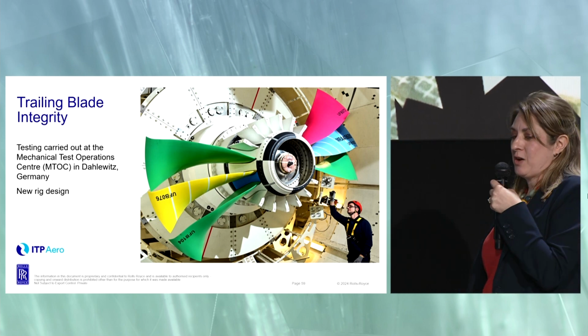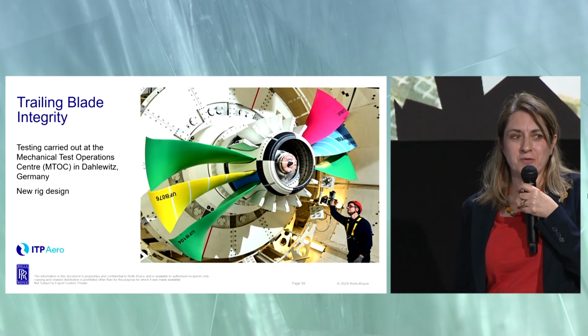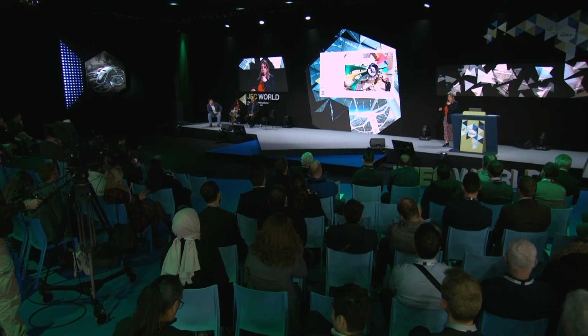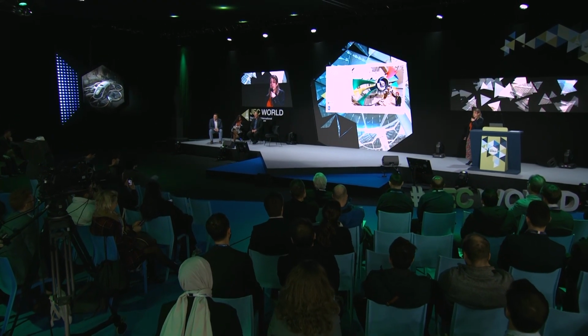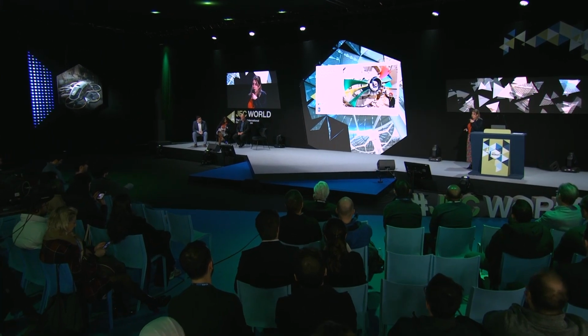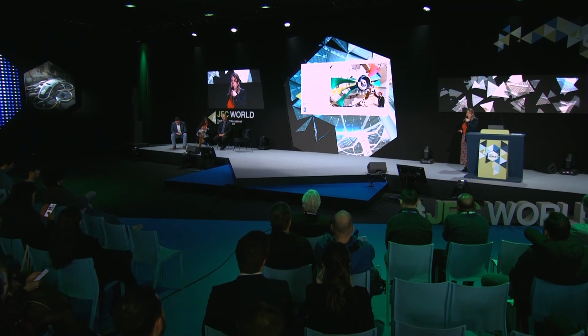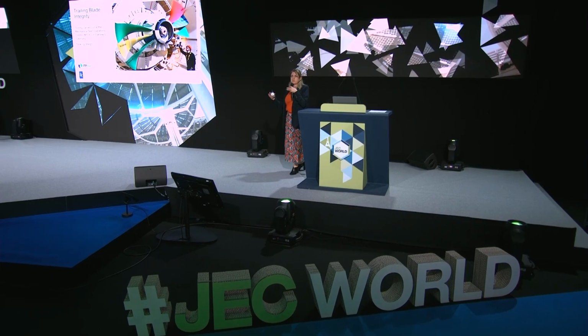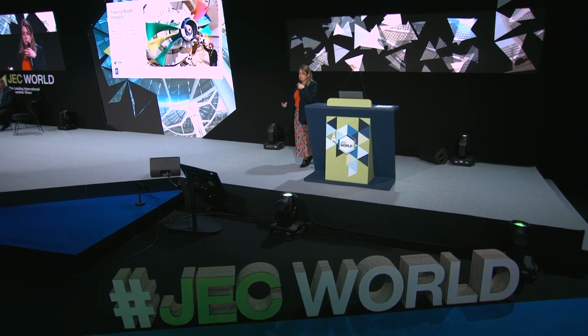The other testing I would like to briefly talk about now is, just before Christmas, we did our trailing blade integrity test. For UltraFan, this has meant a completely new rig, which we have designed and built in association with ITP Aero. The testing is carried out in a vacuum vessel at our Mechanical Test Operations Center, MTOC, on the Rolls-Royce site in Dahlewitz in Germany. What you see is we run with 2 sets of 3 diametrically opposite blades.